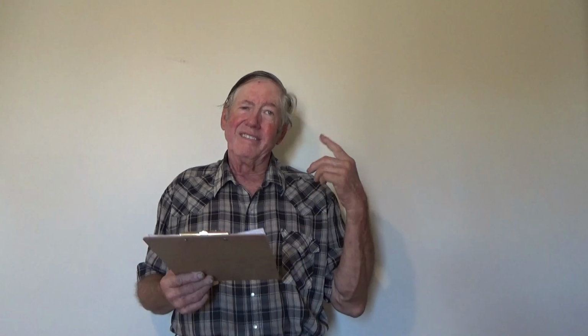Now, to get it out of solution, we tried electroplating it out of solution, didn't work. Too low a conductivity, too low a concentration, something, I don't know. Didn't work. Zinc precipitation has other issues that we would prefer to try and avoid, not the least of which is it's really hard to get clear solution, which you need to do if you're going to do zinc precipitation. And so the most obvious thing would be either resin adsorption or carbon adsorption.